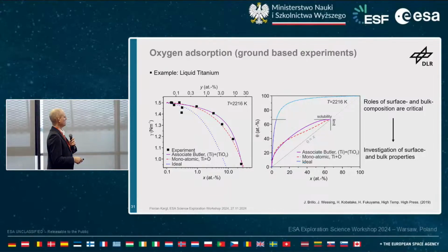Surface tension as a function of oxygen content and at a particular temperature here. Experimental data taken in the laboratory in an electromagnetic levitation facility. And you see the experimental data points here. Relatively constant initially, up to about 1 atomic percent oxygen, which is quite a lot. But the reason is that titanium gathers the oxygen, takes up a lot into its volume.